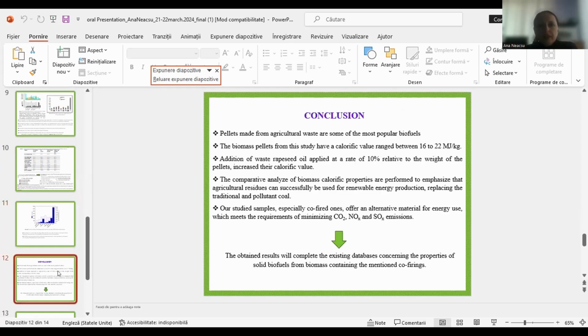In conclusion, the pellets made from agricultural waste are some of the most popular biofuels. The biomass pellets from this study have a calorific value range between 16 and 22 megajoules per kilogram. Addition of waste rapeseed oil applied at a rate of 10% relative to the weight of the pellets increases their calorific value. The comparative analysis of biomass calorific properties is performed to emphasize that agricultural residues can successfully be used for renewable energy production, replacing the traditional and polluting coal.